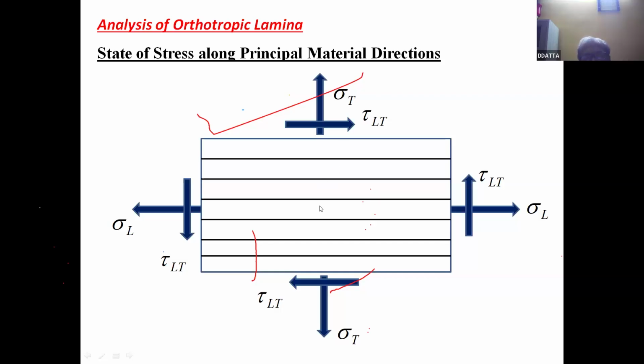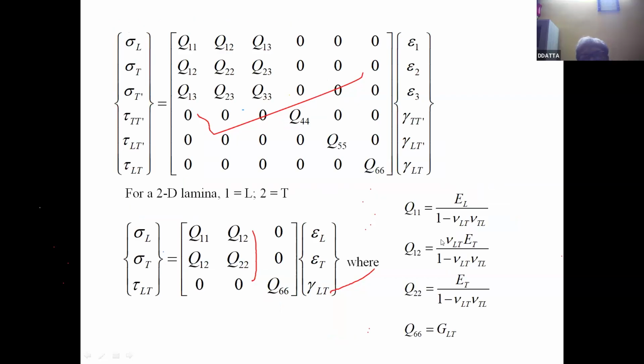So EL in this direction and EL in this direction are the same, and ET in this direction and ET in the bottom direction is also the same, because they have planes of symmetry. So if we look at the stress-strain relation, this is the three-dimensional one, but when we reduce it, it looks like this: sigma L, sigma T, tau LT, Q11, Q12, 0, Q12, Q22, 0, 0, 0, Q66.